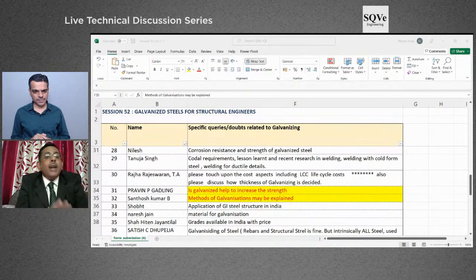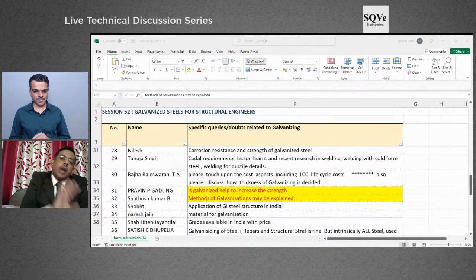There you need to have batch galvanizing, where you have better control and a slower process, but you get a good coating. In automotive or continuous galvanizing, the basic difference is that the coating thickness is very low. It is about 8 to 10 micron. It maximum goes up to 120 to 140 GSM, gram per square meter. But in the case of batch galvanizing, your GSM or the amount of coating is quite high. It is above 200 in most cases.